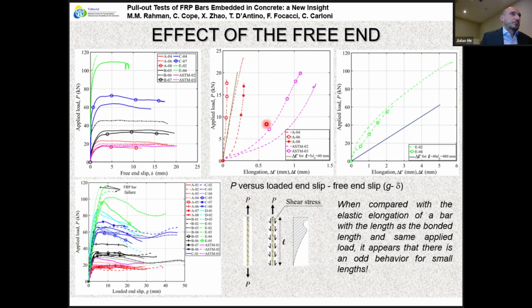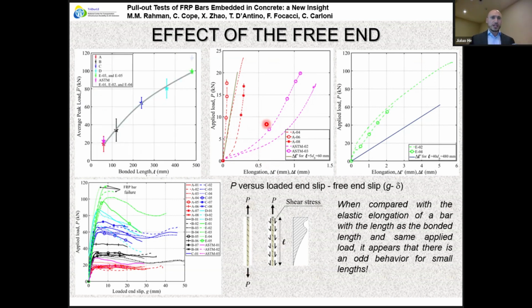Which was not possible, mechanically impossible. So we tried to understand why only when you increase the bonded length, you see this difference. I want to mention here that this is the peak load versus the bonded length, and you see this trend, and the fourth length, the 30 diameters, was slightly off.